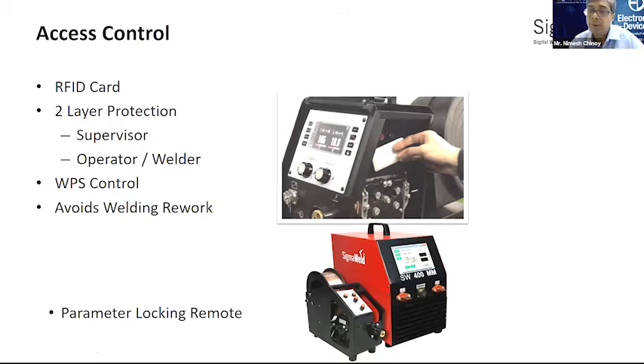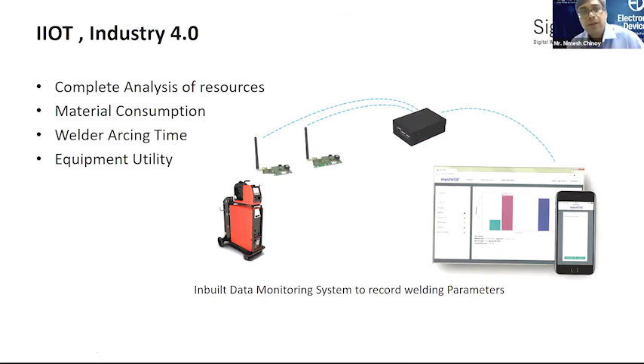We also have old parameter locking remotes which were in our traditional equipment to do the same thing. We were able to help one of our customers who was in the auto sector. Their rejection rates were up to 13% per day. We could bring it down to 0.3% per month simply by locking the parameters the welders couldn't change. So if the welder is your regular one or is a contractual welder, you still have no issues because he is welding on the parameters you have set.